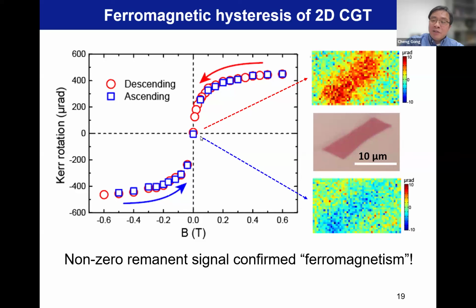Why is the remnant small? Simply because the domain size is small, usually on the order of tens of nanometers, but the laser spot for this measurement is micrometer size. So you will always measure the average result over tens or hundreds of domains. That's why you have reduced magnetization. But if you have a fine resolution, like based on an electron beam, going down to tens of nanometer size, I believe you will get a perfect square shape hysteresis loop.